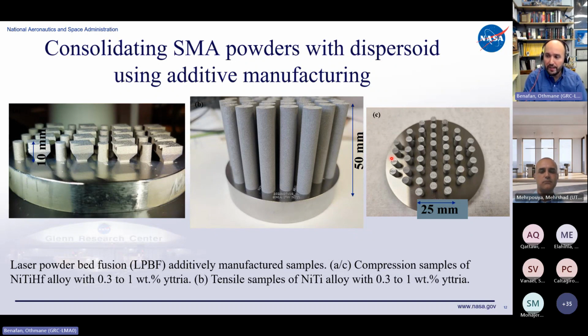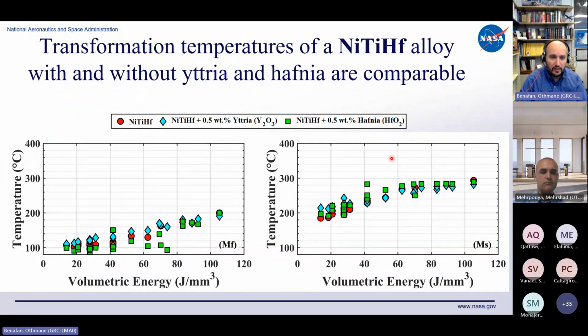When we look, the goal is, do we vary transformation temperatures by doing that? And this is the result. These are alloys with hafnia and yttria, and those colors match. What you see here is with respect to the base alloy, and here I switched just to give you another example. It's not nickel titanium, it's nickel titanium hafnium. So you can apply it to nickel titanium hafnium, maybe iron alloys as well. And you can see that transformation temperatures are within the noise of the bulk alloys. We don't change them that much. So this is not precipitation strengthening, which you would expect to change the alloy's chemistry and therefore the temperatures. Here you can keep the transformation temperatures as is as you develop the next phases. So that's check number one. Transformation temperatures are achieved and we're not affecting them that much. They are within target.